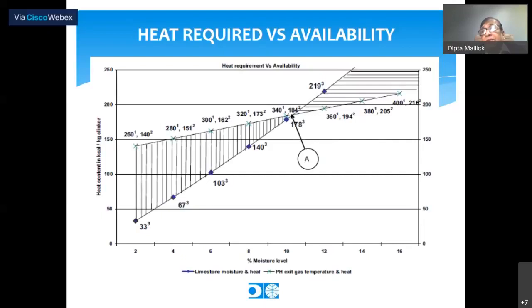Here is a chart which shows the amount of energy available in the preheater exhaust gases, and the amount of energy that is required for raw meal drying. You see that if it is 2% moisture in limestone, then you have 140 kilocalorie per kg of heat available in the exhaust, whereas your requirement for drying is only 33. So you have about 107 kilocalorie per kg of heat available for doing some other useful purpose.